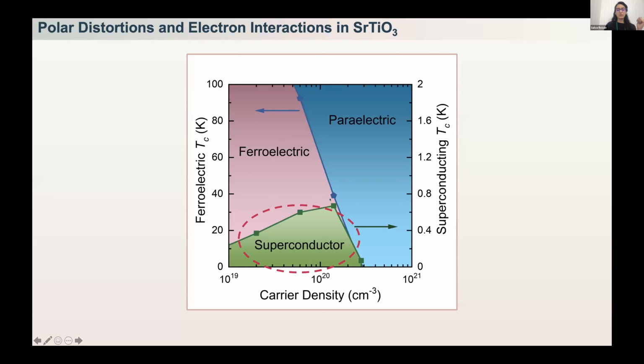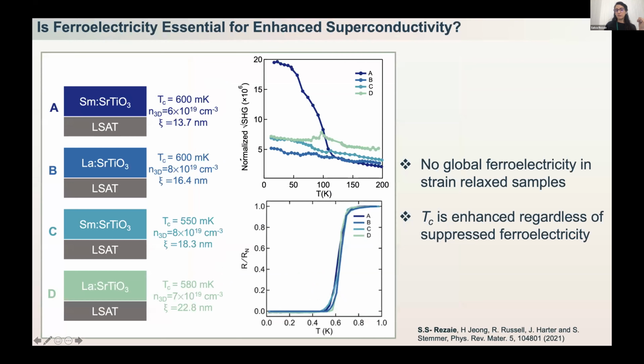But what about the superconducting state? Can we still say why the structures where superconductivity has emerged from the ferroelectric state have enhanced superconducting critical temperature, as opposed to ones that have not emerged from the ferroelectric state? And what is this connection between these two? For that, we engineered different structures. We tried to have films with very similar superconducting critical temperature. As you can see, all of these films have enhanced superconducting critical temperature, and the carrier density in all of the films is very similar.